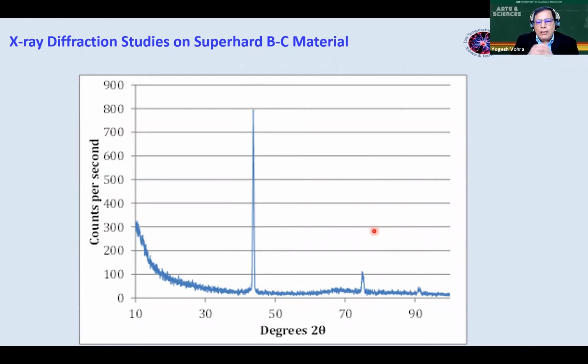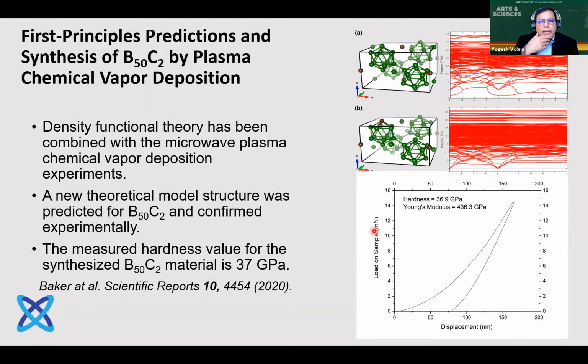So the summary is that the BC5 crystalline structure remains still elusive in our CVD experiment. But we have produced a very heavily doped diamond material. Moving on now to a boron-rich compound.